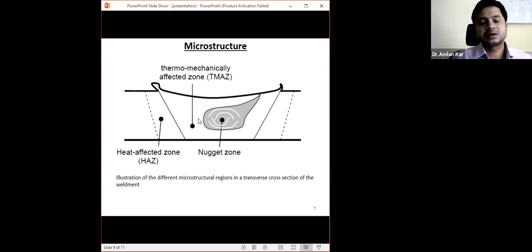But since the temperature evolution in this particular case is much lower than the melting point of the material, the problem due to solidification does not come into the picture. And since the temperature is very low, you can overcome the residual stress substantially. Therefore, this is the process where you can develop the local composite in a particular location where you need improvement in the mechanical property.